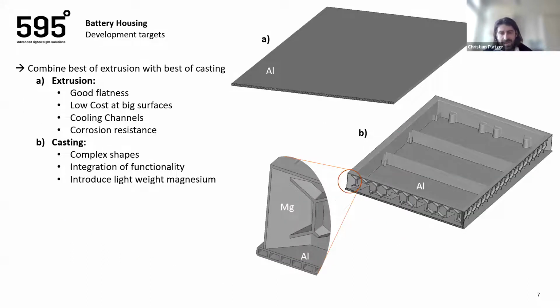And now I would like to come to the thing that we are doing or trying to do. We are trying to combine the best things that we can get from aluminum and from the extrusion process with the advantage from magnesium and casting. We are using the aluminum profile for the basis of the housing because it provides us with good flatness at low cost, even in big dimension. We already have the cooling channels inside, and they are ready to be flown through with the coolant. And the disadvantage of the profile is that you cannot bring functionality and complexity into the geometry, but this we can do with the casting process.